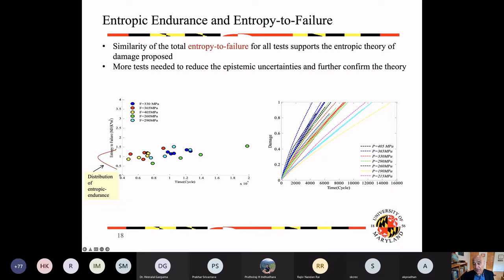over time, each of these curves shows the cumulative damage accumulation from time 0, which of course wasn't completely 0, because some of the units already had some damage to start with, but ends at the normalized value of damage. Note here, everything is normalized to this point. So the damage starts from 0 and ends at 1, 1 being the point that a crack of 250 micron has been observed. So there are 16 experiments here, and then you can see the results here.